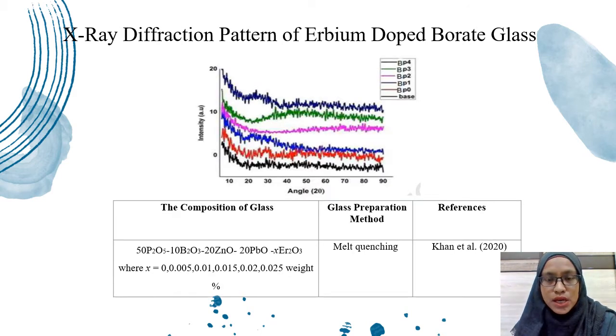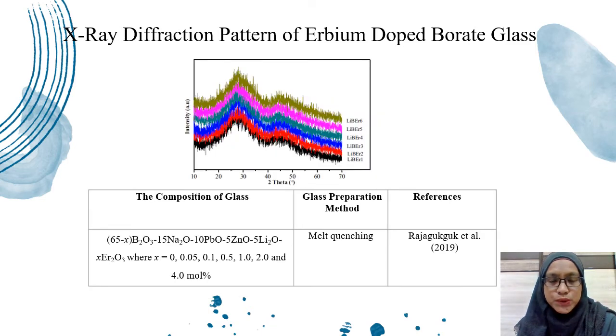Borophosphate glasses containing erbium by Khan et al. 2020 was spotted and pointed out the presence of broad humps. The pattern reveals the amorphous nature of the glass. The XRD pattern by Rajagukguk using the melt quenching method shows different shapes and a broad diffraction peak. The broad peak revealed that all samples are amorphous in nature.